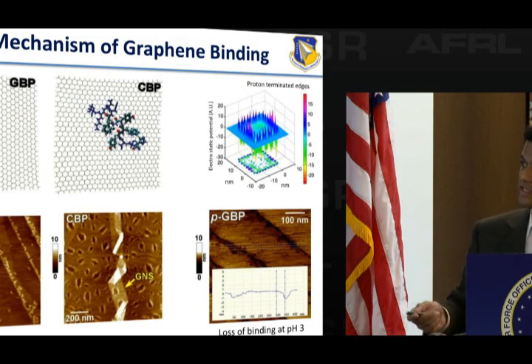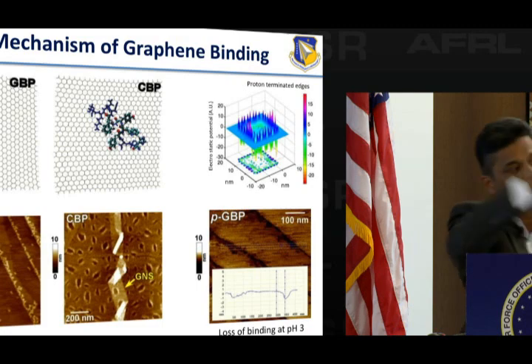We know that this, for example, this peptide is very pH sensitive. So if I flip the pH, if I go to acidic pH, I can knock off those peptides from the surface, and they actually go onto the plane. So they go from this edge onto the plane. This white area that you see is actually the peptide that's come off and actually gone there.